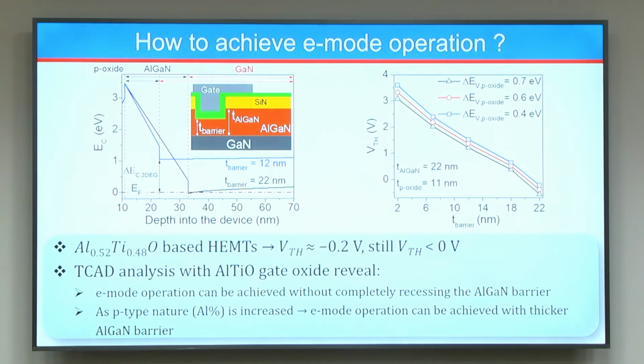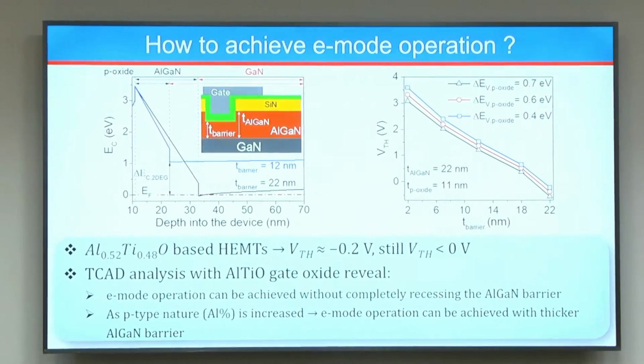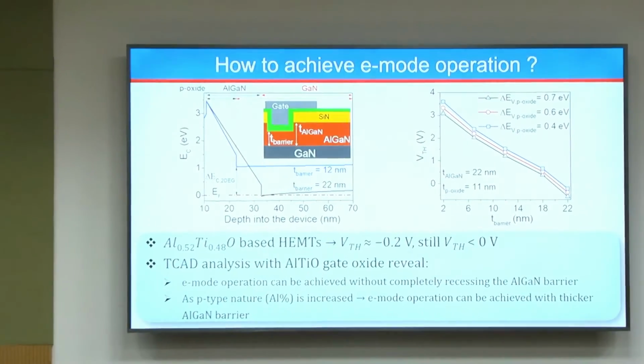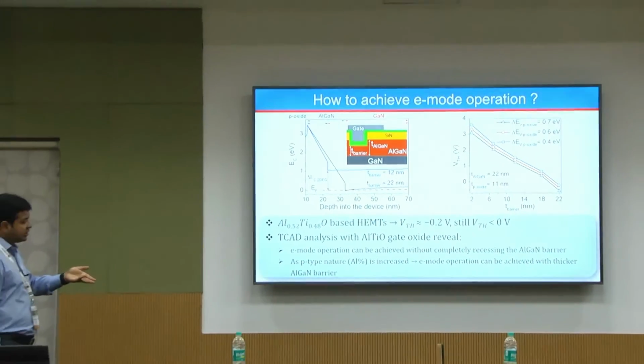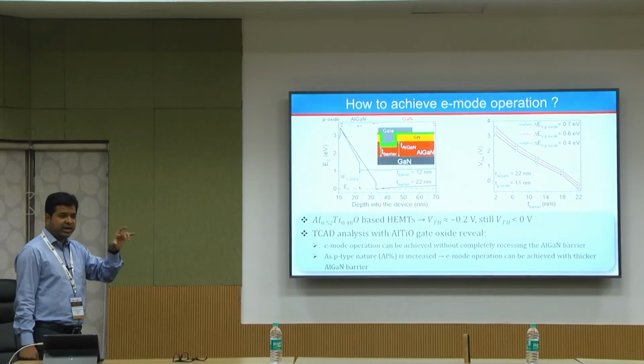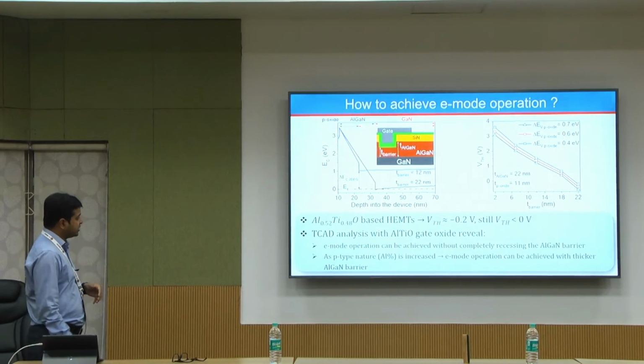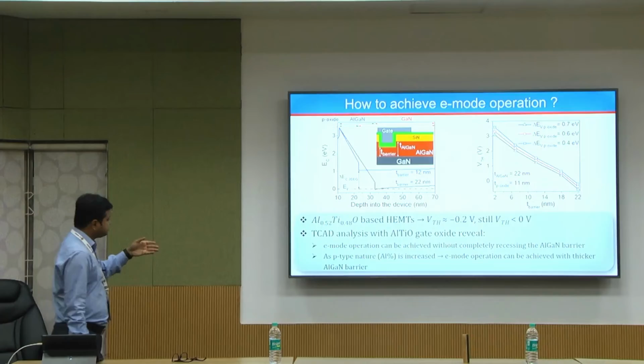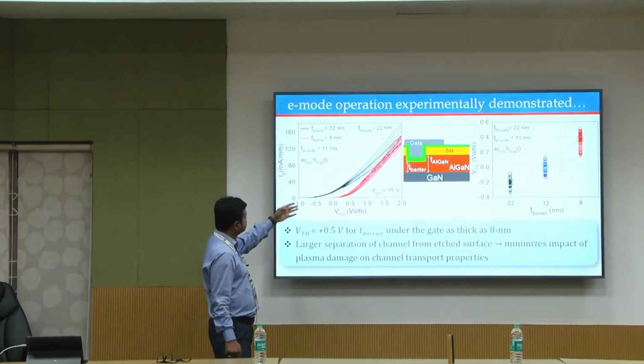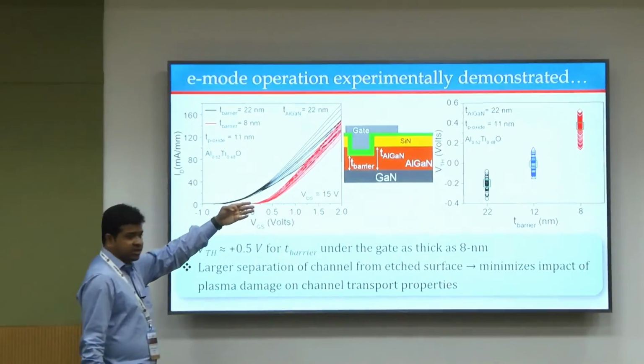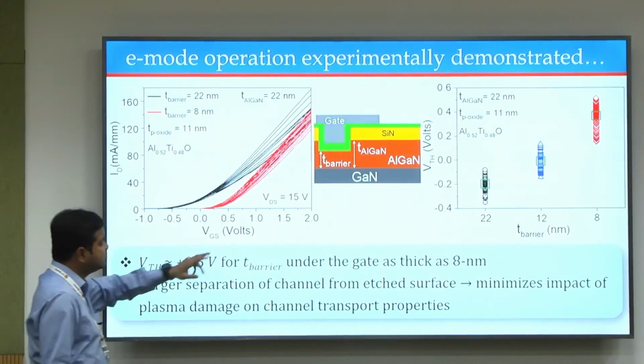And so now we were around minus 0.5 volt of threshold voltage. This is for the case when the 2DEG concentration is very high, meant for D-mode devices, very high current devices, right? So now we have to shift the threshold voltage further. So there we investigated that if you reduce the 2DEG concentration by thinning the barrier locally in that region, you can further shift the threshold voltage, and that's where we introduced the partial recess in the gate region.